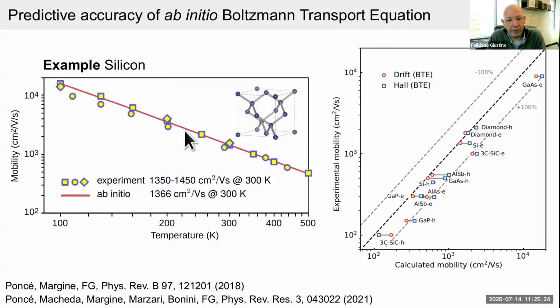And I would like to emphasize that the calculations do not include any fitting parameters. So the only input in these calculations is the atomic mass of silicon and the atomic charge. And you can see that the agreement is pretty spectacular in this case. And that basically tells you how predictive these kinds of calculations have become over the past few years.